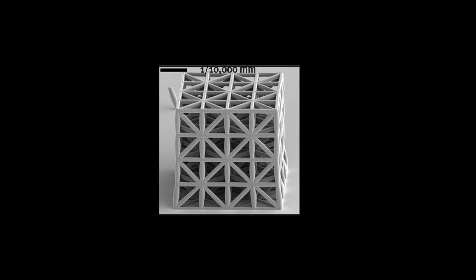As the capacity to process materials on smaller and smaller length scales increases — so we can move down to scales below a micron to a hundred nanometres, these tiny scales — this is where we get to a point where we're approaching the intrinsic strength of our material. And what we see then is that they perform, at least in their individual components, maybe ten or a hundred times better than we would see in a large piece of material.